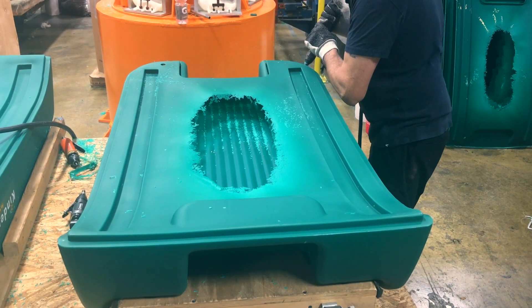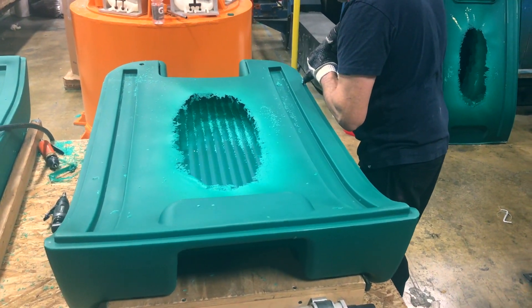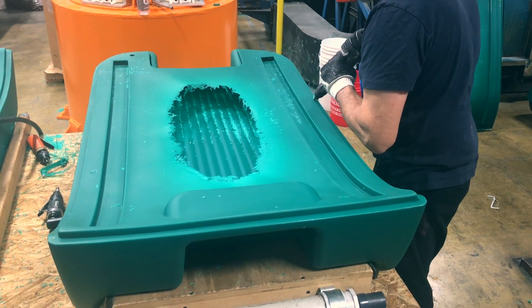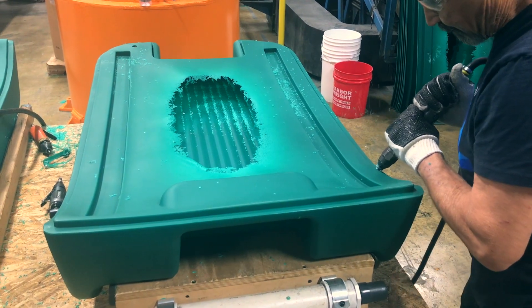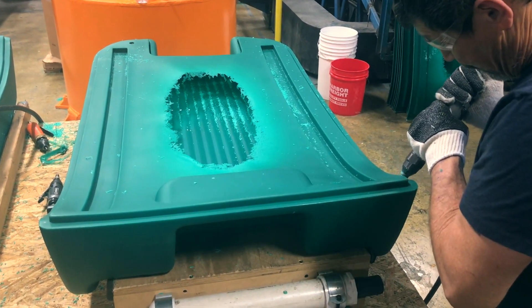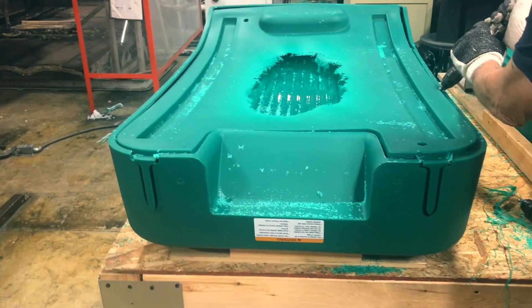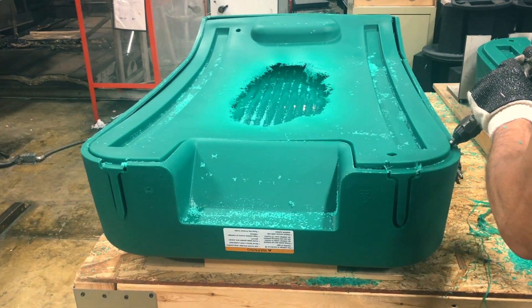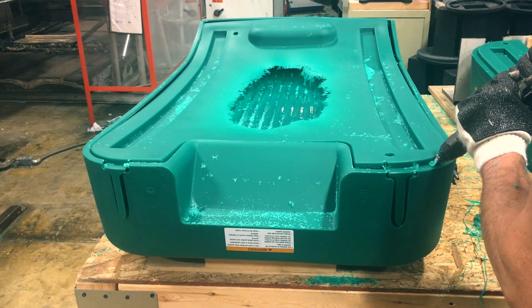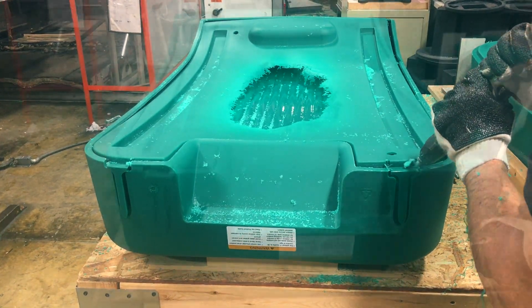A little background on this job while the part is being trimmed. It was originally designed and manufactured for thermoforming with a weatherable ABS, which worked well. However, the customer requires all of their products to have a lifetime guarantee, no questions asked. Due to continued wear over roadside curbing, the ABS would eventually become weak and break. Therefore, an alternative process was required.